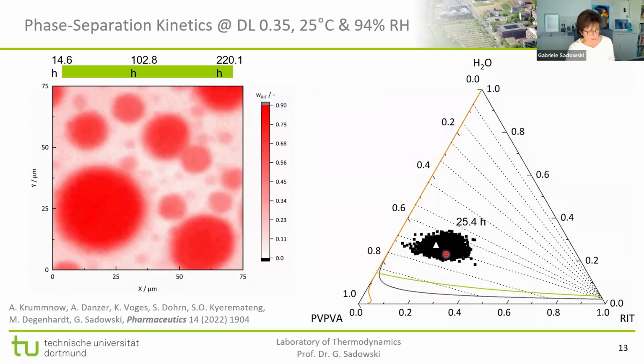These are our Raman data from the same picture, but now in this diagram. And what you see is, if we consider this as a function of time, we could really see the system demixing. So the system does demix, and it not only demixes, but it demixes along the tie lines we have predicted. These are the dotted lines here. So that means the sample does what we thought it would do after absorbing water. It moves from a point down here, which is homogeneous outside the miscibility gap, but absorbing water during dissolution at very high RH, we will move into the demixing area, and so the system will demix.